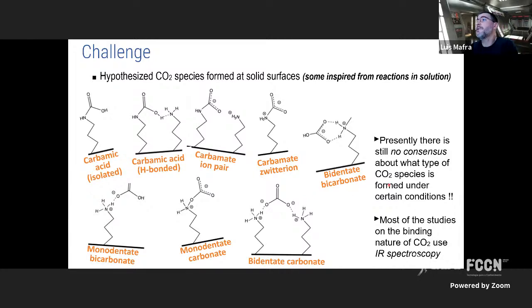Traditionally, a lot of work has been done with infrared spectroscopy, but the materials are not transparent to infrared. You have matrix effects, you have huge band overlap, and all of you know how difficult it is to really understand speciation, different functional groups which are very similar across these different entities. It's basically an impossible task. Apart from that, these species are often very dilute on the surface, so you need a very sensitive technique, and NMR is very insensitive by nature. Another problem is that the chemical shift window is very narrow as well. There is also a lot of overlap in NMR chemical shifts, in carbon specifically.